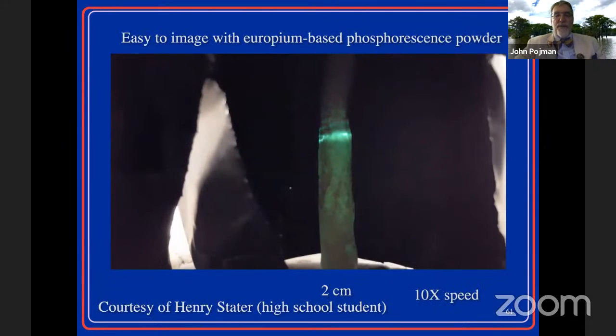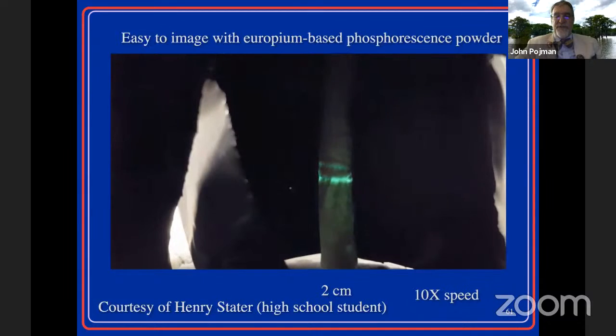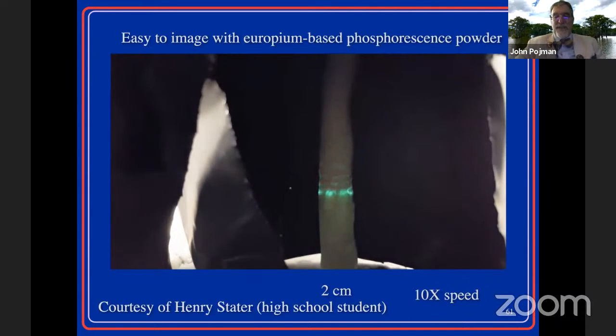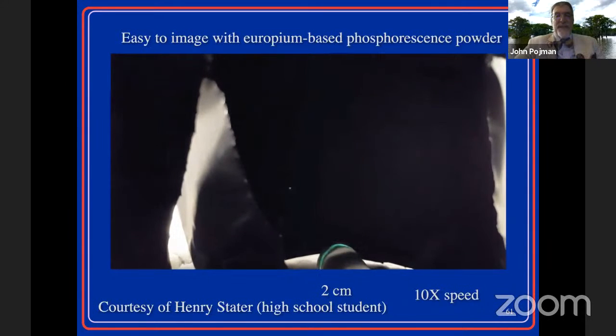And this is a nice experiment where we take an acrylate system and we put a glow-in-the-dark powder, a phosphorescent powder, on the surface, and it glows brightest when it gets hot. And so this is sped up, as you can see, this reaction is going around and around in this helical pattern. There's no easy way to explain this in terms of chemistry. It has nothing to do with chirality. You can have all of this if you just simply have A produces B and gives off heat with an exponential dependence on temperature. And all these kinds of behaviors can be seen.